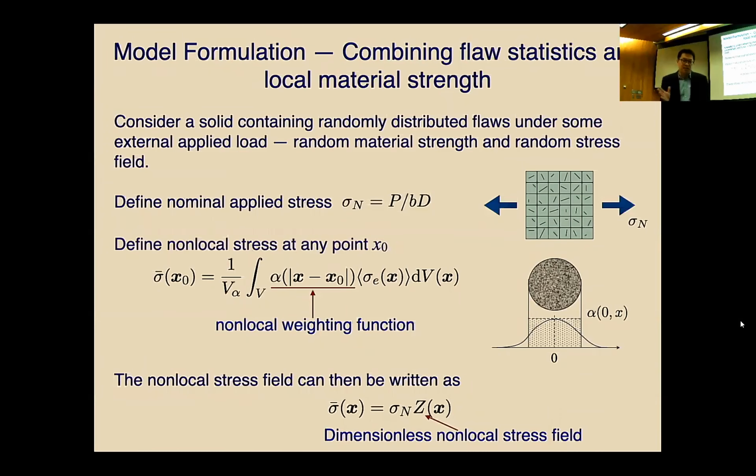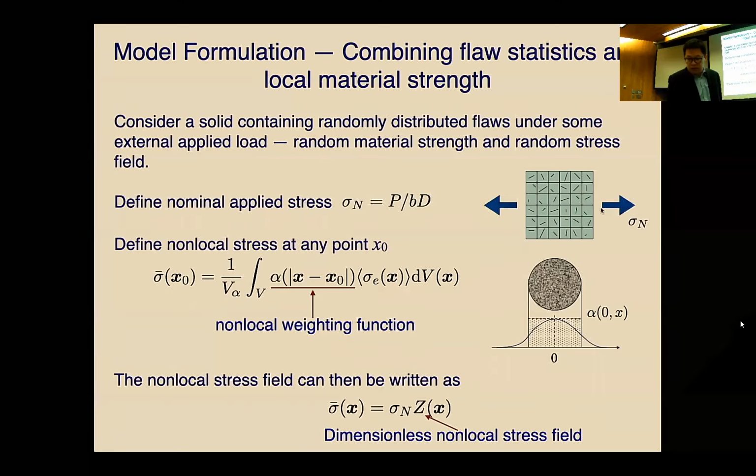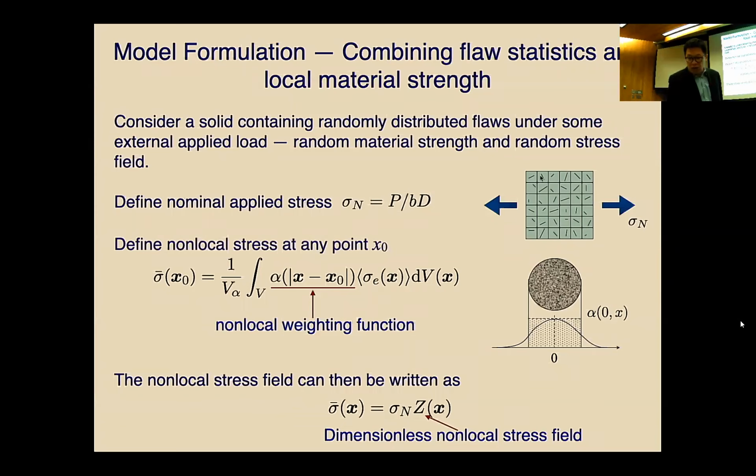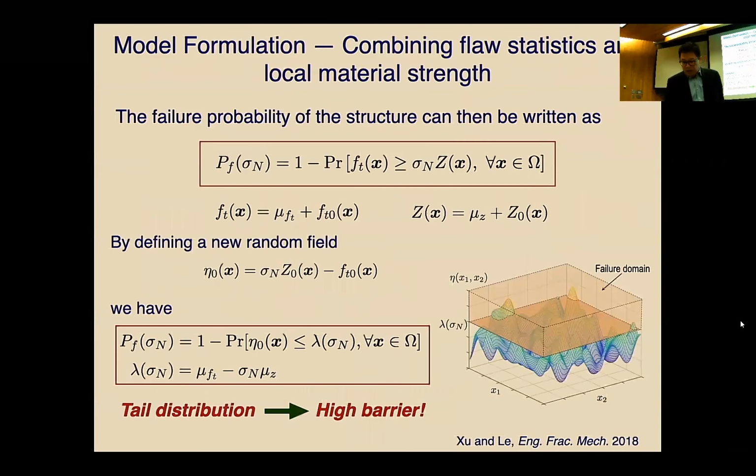I will skip this part because the non-local criterion is exactly the same as what we proposed for the MEMS structures, but now it's in 3 dimensions. Basically, again, what we have is the non-local stress equal to strength, and we want to determine the peak load of the specimen. The peak load of the specimen is reached when any one point in the material satisfies this failure criterion. So it's a very similar idea, but now it's high dimension. It's not 1D anymore, it's 2D or 3D.